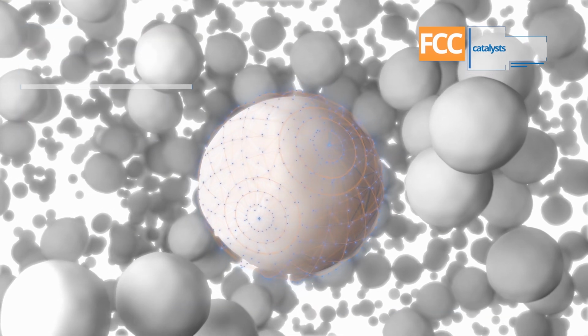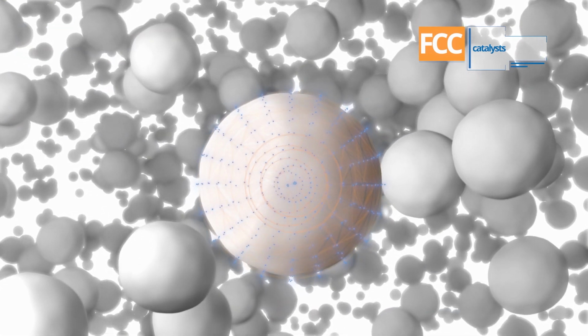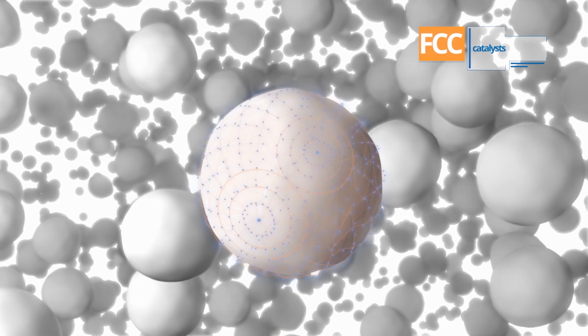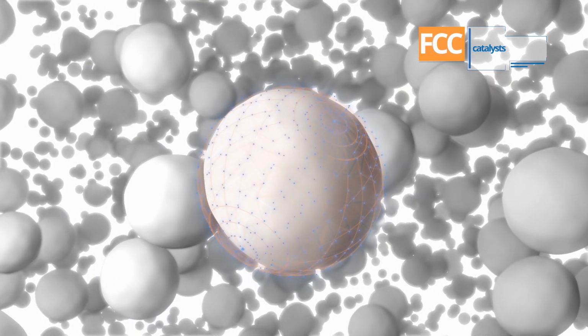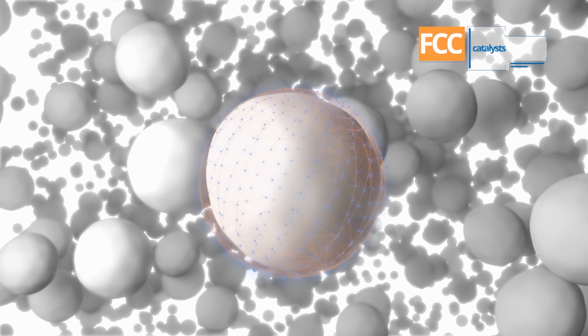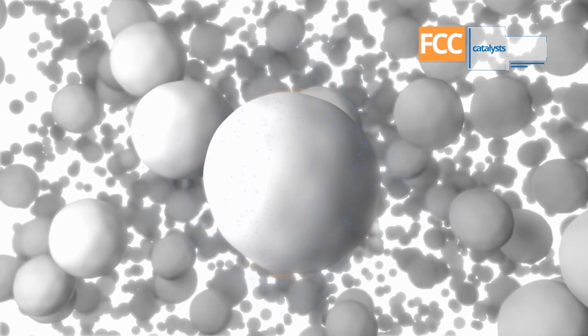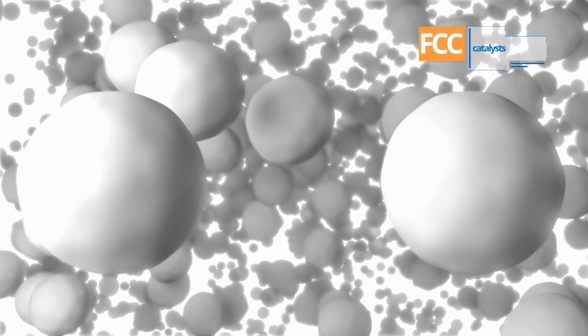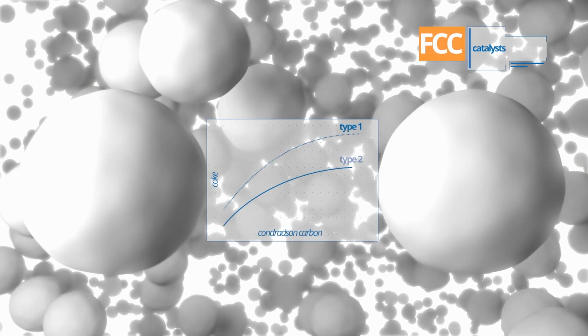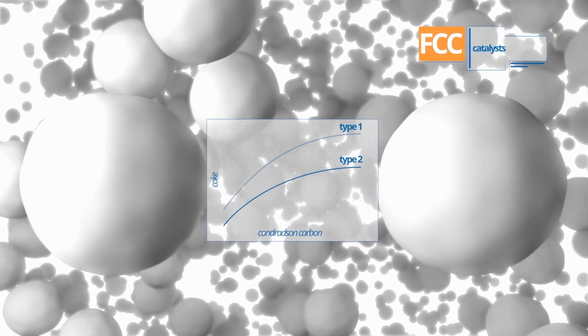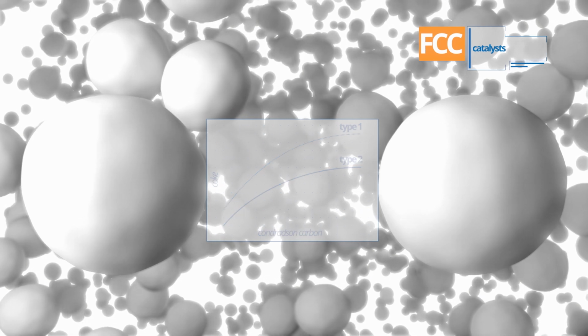the catalyst pores. The KNT Group's novel matrix technology provides a controlled matrix pore structure and acidity, acid site type, strength and density, and as a result it is used to vary the catalyst coke selectivity across a wide range, from minimum delta coke to process heavy feedstocks to maximum coke selectivity to convert low Conradson carbon feeds. The synergistic effect is the result of using superior zeolite technology together with active matrix, where the activity achieved by their combined action is higher than the sum of their individual activities.